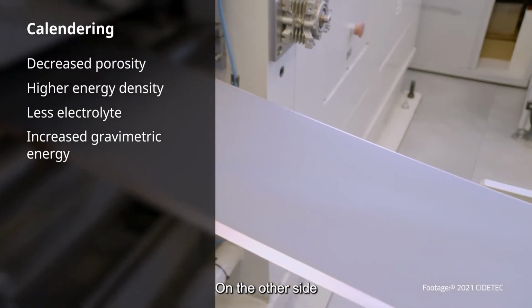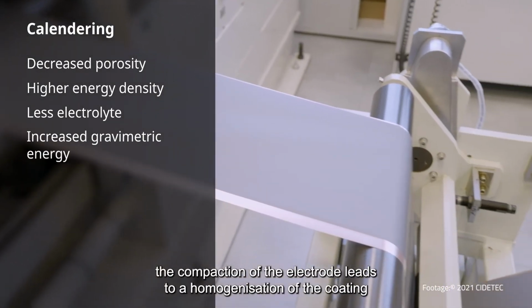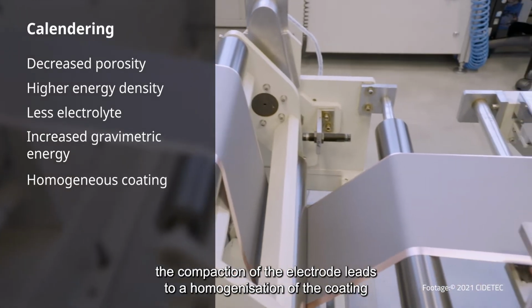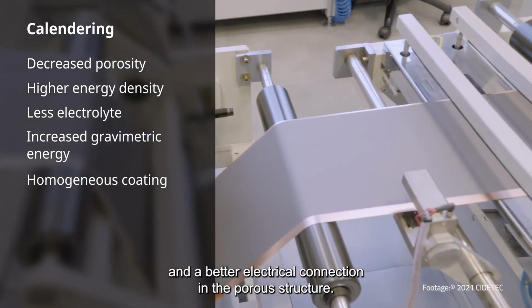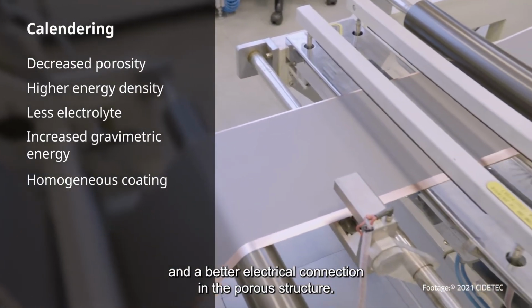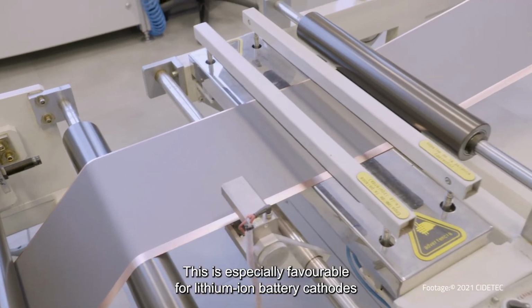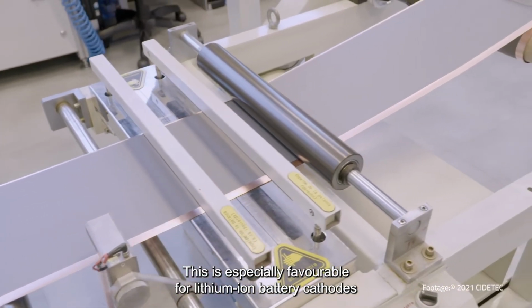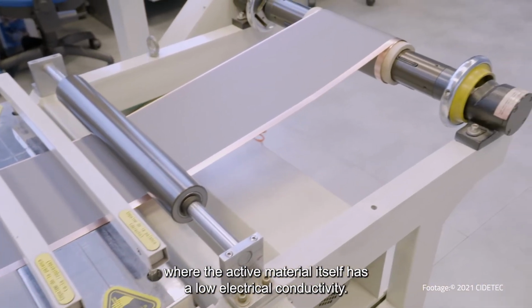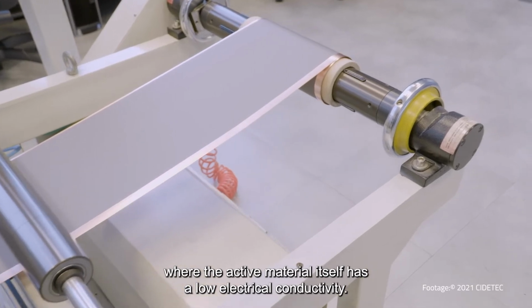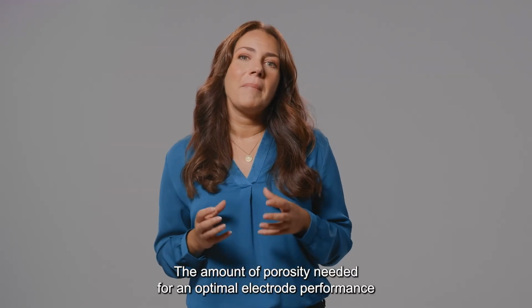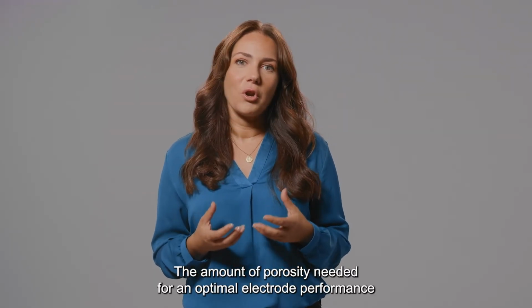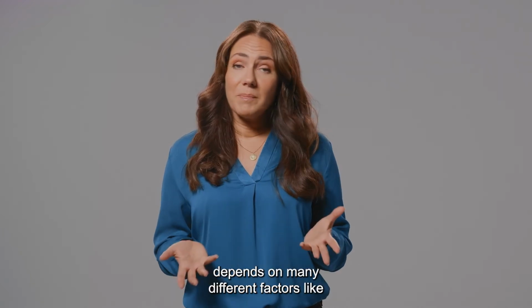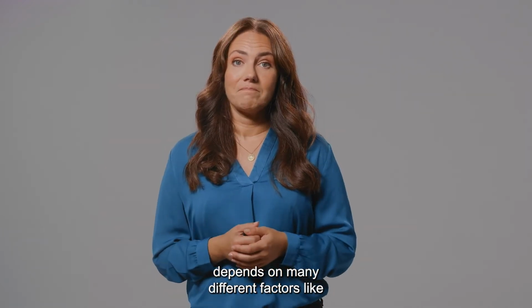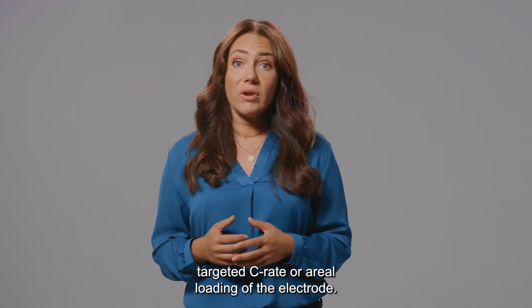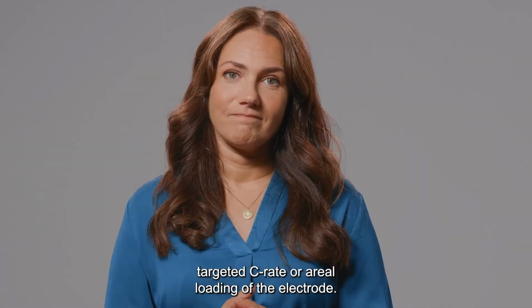On the other side, the compaction of the electrode leads to a homogenization of the coating and a better electrical connection in the porous structure. This is especially favourable for lithium-ion battery cathodes, where the active material itself has a low electrical conductivity. The amount of porosity needed for an optimal electrode performance depends on many different factors like targeted C rate or area loading of the electrode.